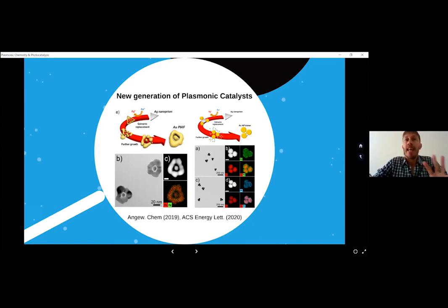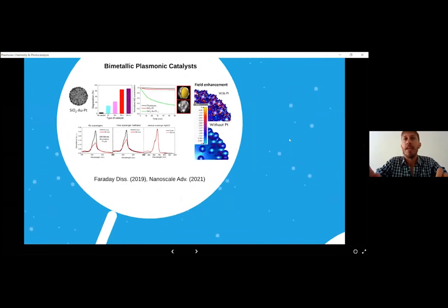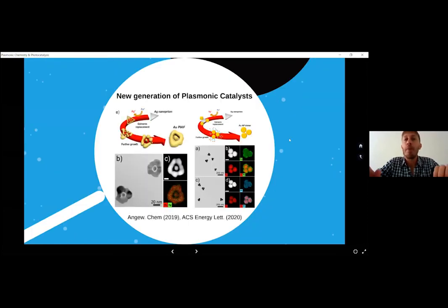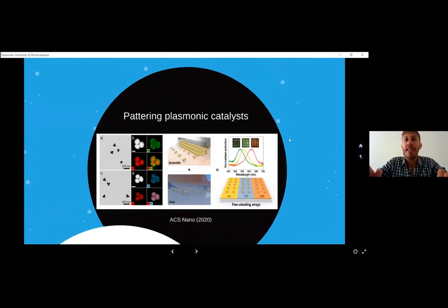So finally, the last thing regarding colloids that we designed and fabricated for plasmonic catalysis, oops, sorry, come back. The last thing is that we started thinking about patterning surfaces by using these colloids. The idea of patterning surfaces is that when you have these plasmonic colloids, and you want to perform chemical reactions by using the colloids in solution, there is a problem with the penetration depth of the light inside the solution of colloids. If you have a really concentrated solution of colloids, what might happen is that most of the light gets absorbed by the first layers of colloids, but then in the bulk, inside the solution, the catalysts will not have any kind of illumination, right?